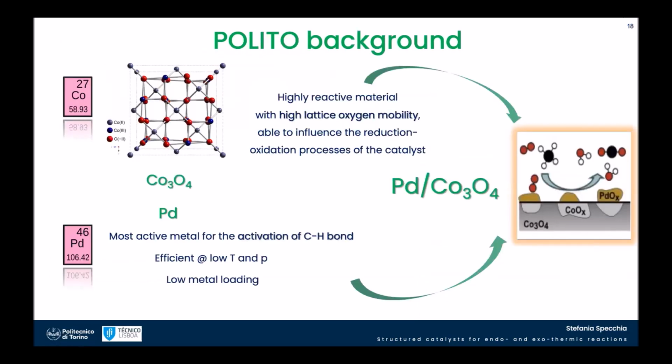In the past, within the group I'm leading, we worked a lot on methane combustion, and we tested many different catalysts, but we found a very interesting option by letting work in synergy palladium, in reality palladium oxide, in combination with a cobalt spinel oxide.